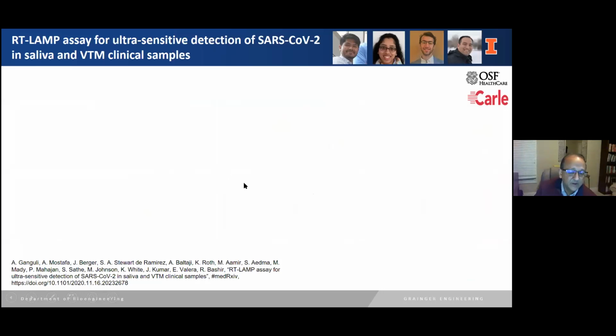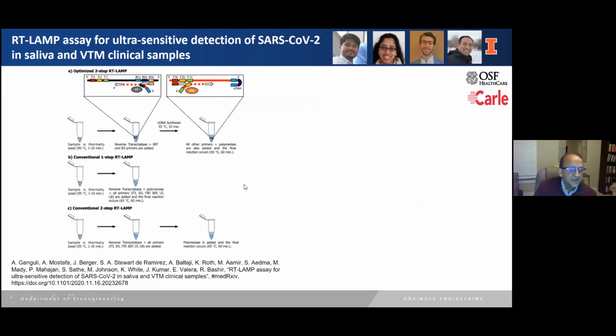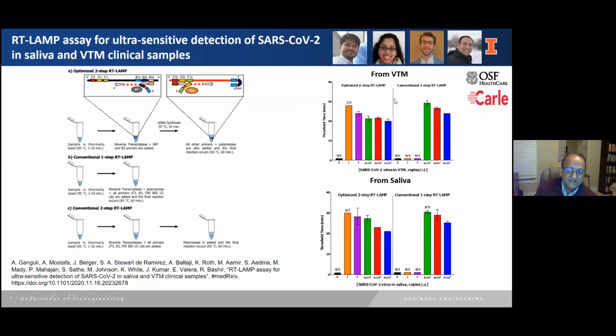and hopefully should be out for review soon, where we further optimized the RT-LAMP process to make it even more sensitive by adding a two-step process, splitting up the cDNA synthesis step. Using that, we improved the sensitivity of LAMP from VTM and from saliva. We also measured this from saliva, and it works quite well.